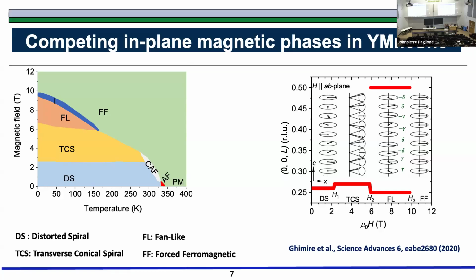So what we did in this work is, in order to know how these structures are arranged in the material, we used neutrons. Neutrons have a moment, right? The spin of the neutron can interact with the ordered spin, in a very similar fashion as we use X-rays to know the crystalline structure. We can know the ordered structure of magnetism in materials by using neutrons. And we collaborated here at NIST with Jeff Lynn and his group. And then we determined the magnetic structure, and we needed some help from theory also. Sometimes theory is very helpful, especially as we were having difficulty identifying this fan-like phase, and my colleague at George Mason, Igor Mazin, came up with this structure by pure calculation, and then it matched perfectly with the experiments.